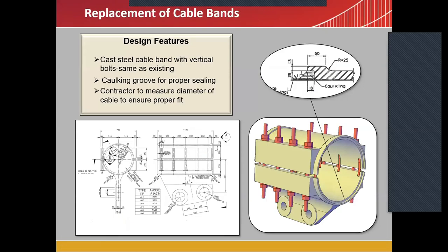Replacement of the cable bands. The cable bands had some problems. We could not even remove the bolts because they were bent. That's why we designed new cable bands with proper caulking and sealing grooves. The design features of the new cable bands are cast steel cable band with vertical bolts, same as the existing, caulking groove for the proper sealing, and contractors are supposed to measure the diameter at each cable band location.